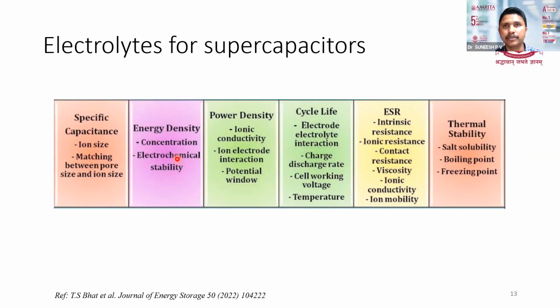Then the power of the device is dependent on the internal resistance of the energy storage device. So the ionic conductivity clearly determines the power density of the device, along with the potential window. If we are providing a very good potential window, that will cater more power density from the device. Then the cycling life is dependent on the temperature, electrode-electrolyte interaction, charge storage rate, and all these things are involved in the cycling life of the supercapacitors.